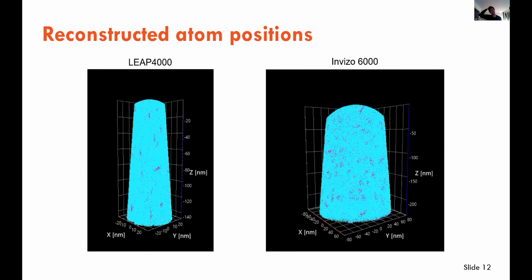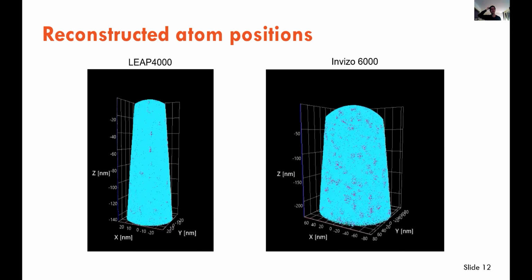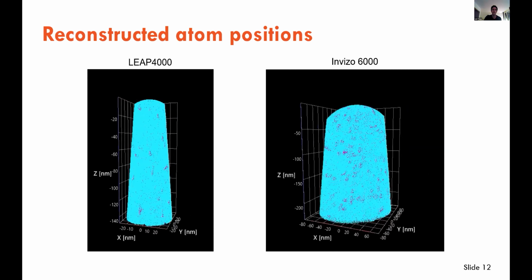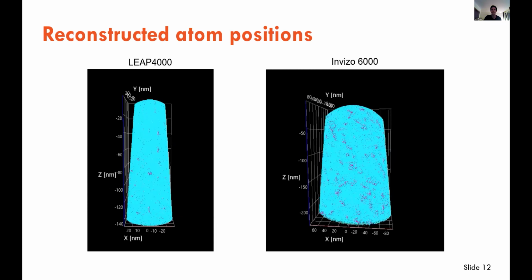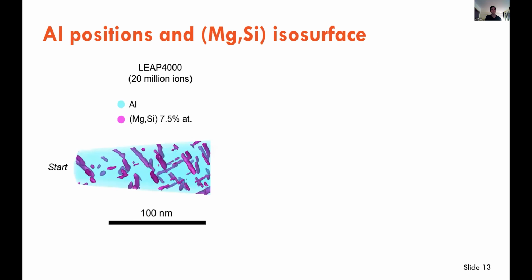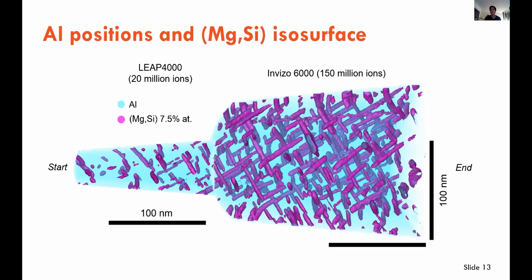So these are reconstructed atom positions, but I don't think these really illustrate the effect of the field of view from the Invizo. So let me do a different type of visualization. The blue dots show the aluminium position, and the purple surfaces are magnesium silicon iso surfaces. This shows the reconstructed data from the LEAP 4000. And then, because the tip in the Invizo was essentially a direct continuation of that from the LEAP 4000, we can essentially just concatenate, line them up with the precipitates that are continuous in both, and see the enormous change in field of view between the two instruments.